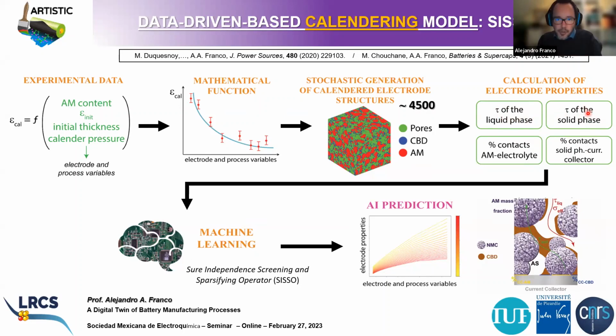We have also characterized the tortuosity factor of the solid phase, which is related to the electronic conductivity of this electrode composite. We have characterized other properties such as the surface area of contact between active material and electrolyte, which is assuming to fully fill the pores. The surface area of contact between the solid materials, the carbon binder domain and active material, and the current collector, and so on and so forth. Based on this data set, where you have as an input these four parameters and as an output all the collection of parameters that you can imagine for an electrode microstructure, we have trained this SISSO-based machine learning model in order to perform regression, okay, in order to predict numbers actually, okay.